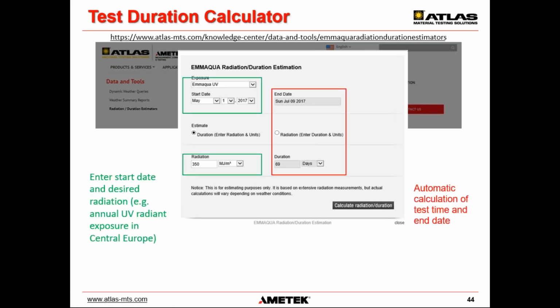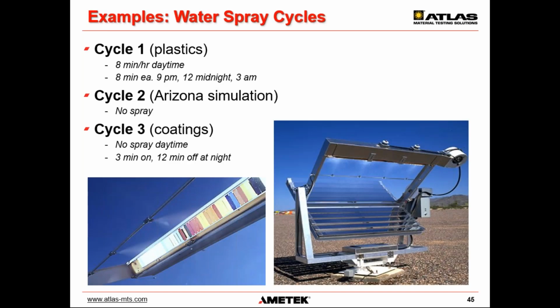As you see there. Now, with this device, we can have different spray phases. Cycle 1, as is referenced in ASTM G90, is a daily, hourly spray during the operation, where for 8 minutes out of every hour, we spray the samples with DI water. This provides sort of a thermal shock, if you will, on the samples.